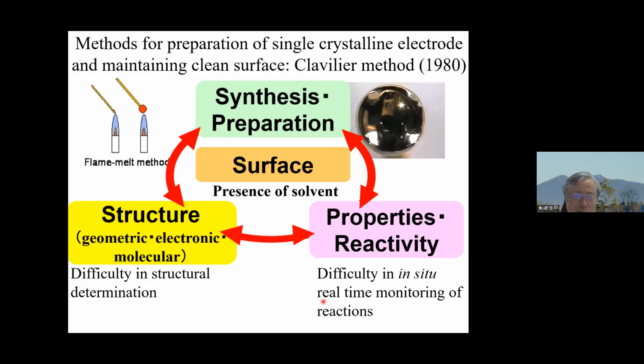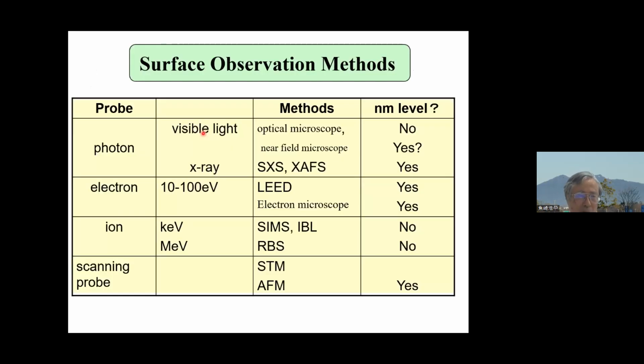But it's already 40 years ago, and our generation really enjoyed this development. In 1980, Professor Clavilier developed a new technique to prepare single crystal beads. Before, single crystals were very expensive and you needed a vacuum system, but he developed a technique to make relatively small but still single crystals. This is the single crystal bead, something like 5 to 6 millimeters. These are the 111 facets. You can use a very nice clean surface, and by using a water drop, you can protect it by the flame melt method.